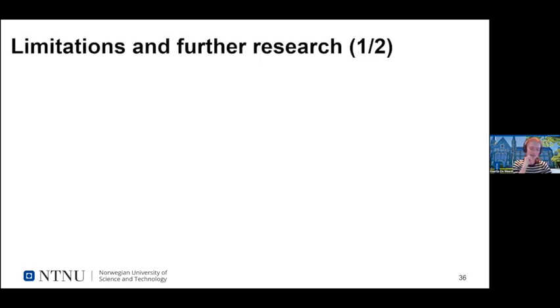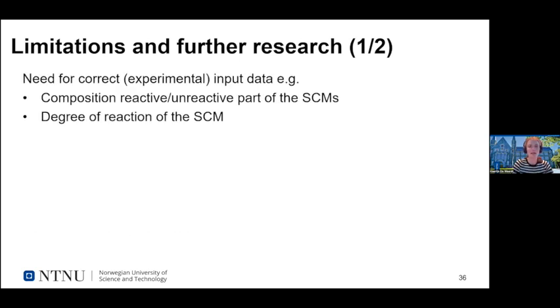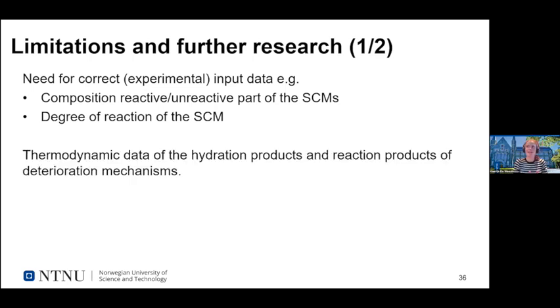First, a little bit on the limitations of GEMS, because GEMS, or thermodynamic modeling, is a wonderful tool, but be aware that you need correct input. So you need to have a good characterization of your SCM to know what the composition of the reactive part is. And you also need to give GEMS the degree of reaction of your SCM, because GEMS does not account for kinetics. And know also that if you don't have thermodynamic data of a hydration product or a reaction product of a deterioration mechanism, GEMS will not be able to predict it. It only predicts the phases you have given it thermodynamic data of.